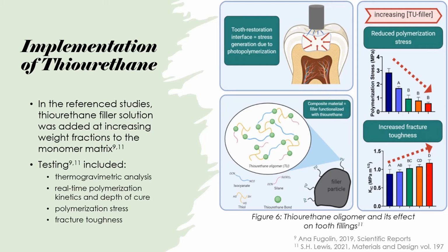This polymerization stress, which can be visualized in the graphic in the upper left, describes the stress which acts on the filler adhesive as the polymer is cured. As it polymerizes, the filler undergoes a volume reduction, increasing the adhesive strength necessary to hold the filling to the tooth and prevent gaps from forming.